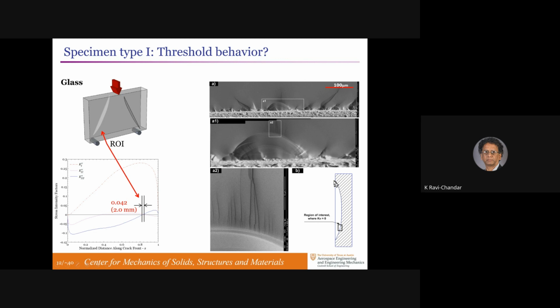The idea was the following. If you slice it in that plane and show the cracked object, this is the cracked part, that's the crack front, and this is all uncracked. It's under a combination of mode 1, 2, and 3. But can you see those lines? Just barely. The mode 1 is about that line. This point corresponds to that little box here. So at this location, the mode 1 stress intensity factor is the largest. So you expect that the crack would start there. On the far side, it won't, because the mode 1 stress intensity will be compressive, so it won't start there.